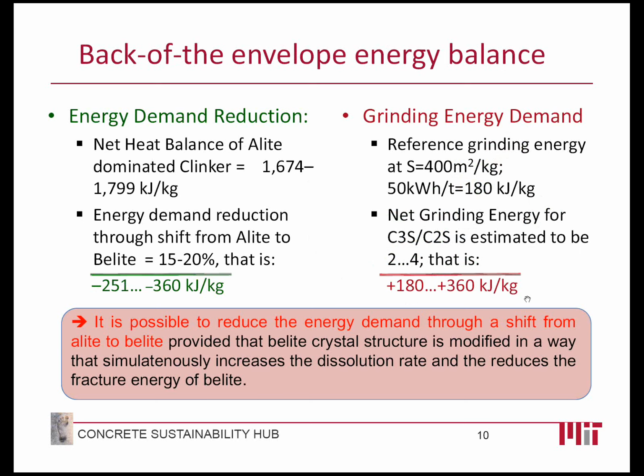Okay, if we go for a back-of-the-envelope calculation, as I told you, if we want to switch from alite to belite, we may have an energy reduction, from a rough calculation, of around 250 to 360 kJ per kilogram. But as I told you, if we are now playing with belite, then the energy required to grind belite is larger. So we have a net grinding energy reduction of, let's say, between 180 and 360 kilojoules per kilogram. So you see, it's pretty meshed: what you get on one side, you lose on the other side. So yes, it is possible to reduce the energy demand through a shift from alite to belite, provided that we do something to the belite crystal, for instance by including impurities, with the idea of increasing the dissolution rate and also reducing the fracture toughness or fracture energy of belite. Next.